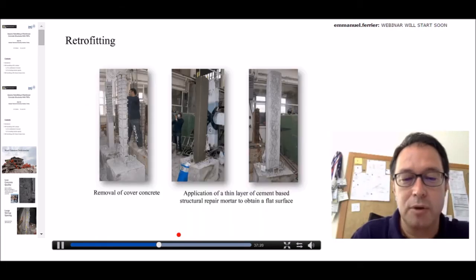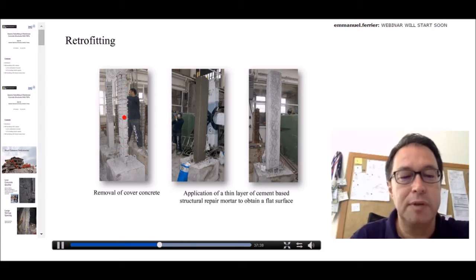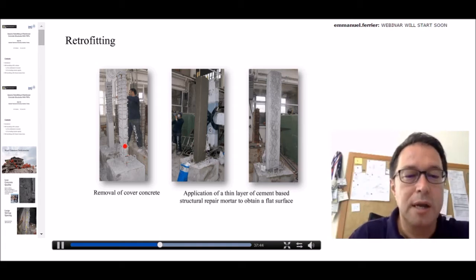Therefore, as I'm going to show you in coming slides, the first stage of retrofitting was removal of the cover concrete. And as I'm repeating again, since we are dealing with very low quality concrete, that's not a big deal. You could do that easily. And in practice, often when you have such a column, another problem is related to the corrosion of reinforcing bars. So these are old columns, not well protected because of the poor quality of concrete and often because of lack of sufficient maintenance and repair work.